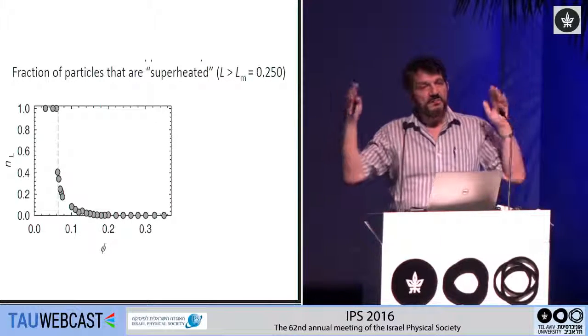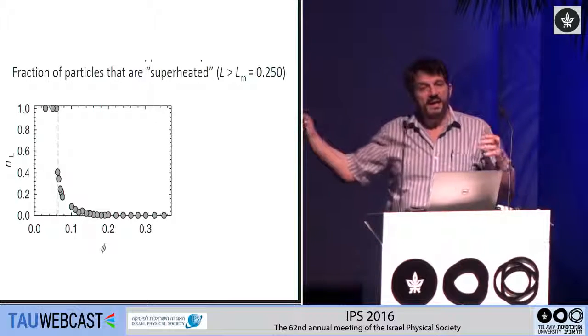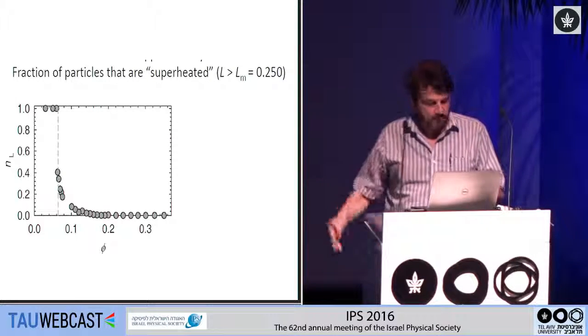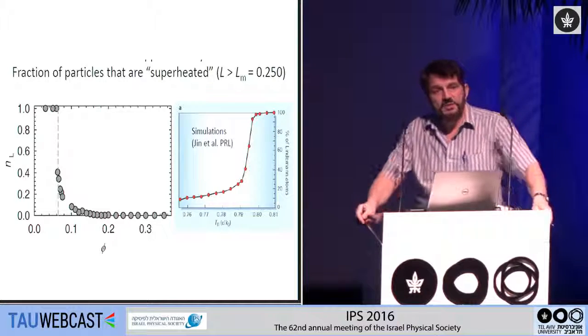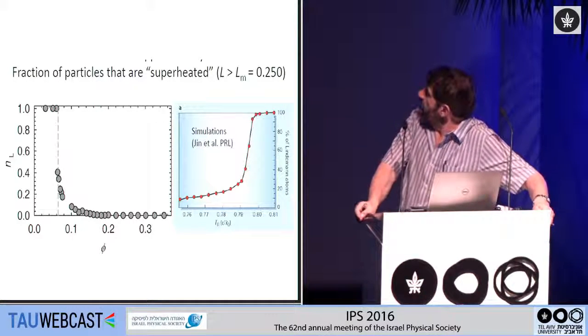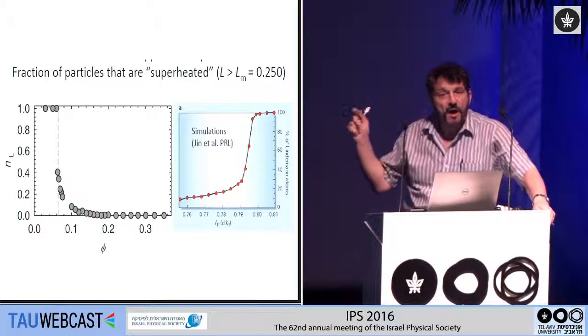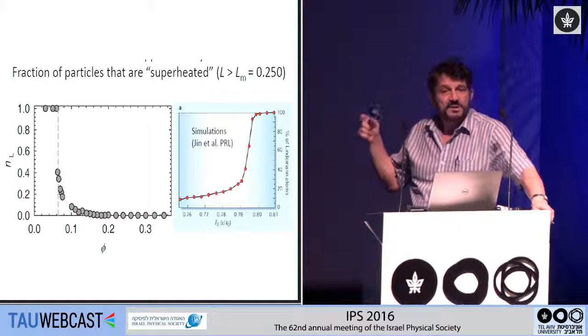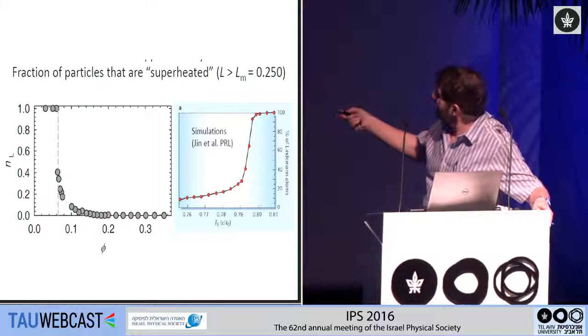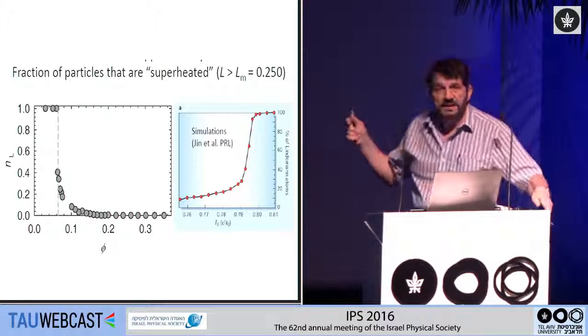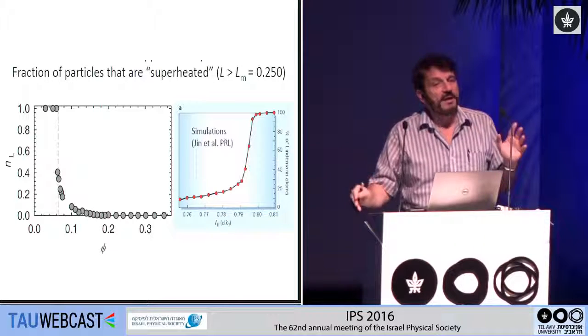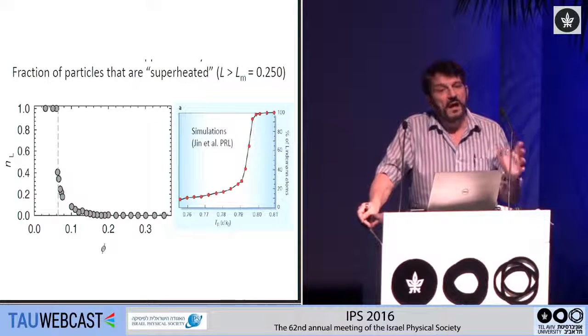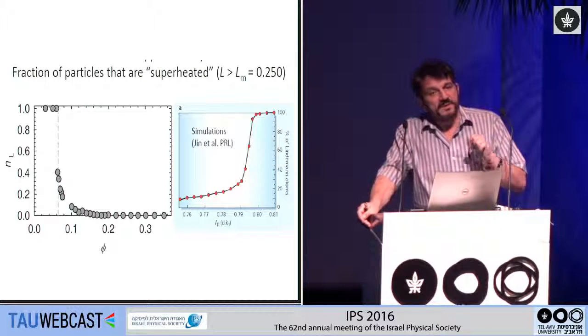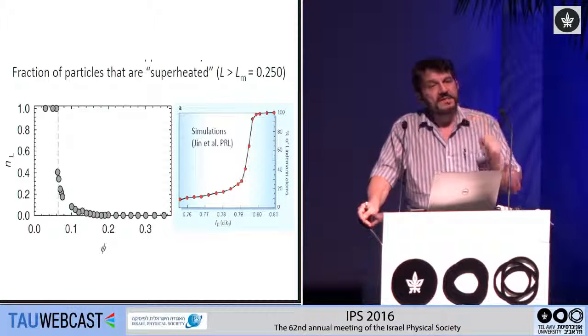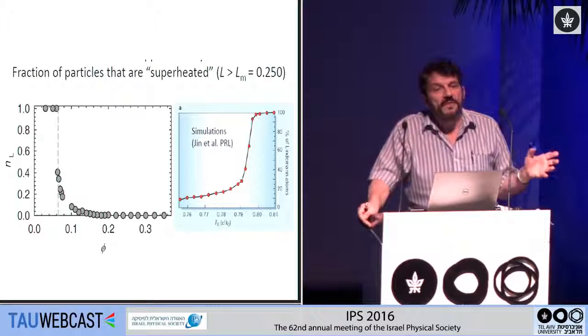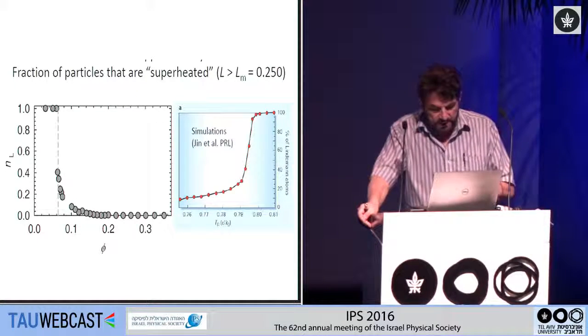So even though you can define an ensemble average value, there are many, many particles that have a much larger value. In fact, the same thing is observed in simulations for metallic copper, using a full quantum mechanical description. You see that as it approaches the melting point, the number of very hot particles becomes much larger. And this is something that you can't see with scattering experiments because you can't really resolve the atomic fluctuations. You can only do the simulations.